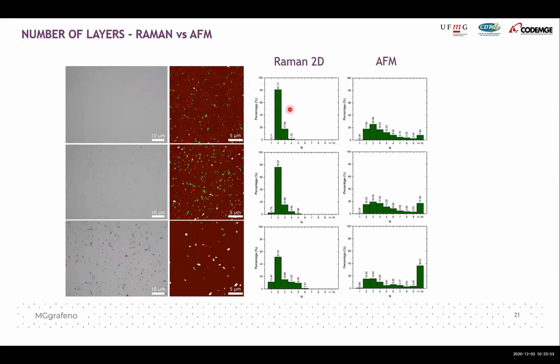So we also put always Raman and AFM. The Raman analysis is also done automatically. So we can also see the material, depends how you look at it. The AFM will be more sensitive to the morphology of the material, and the Raman will be more sensitive to the electronic coupling between the layers. So you can't measure Raman and say, okay, my material is two-layer. This is not true. It is two-layer from the point of view of the electronic coupling between the layers. But it is more than two layers. It has like 4 layers, and it has a distribution if you look at the thickness of the material.